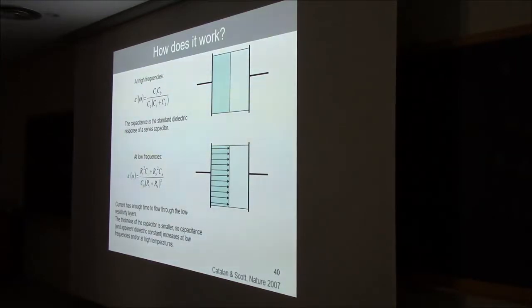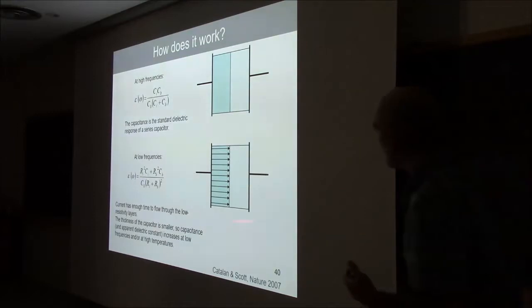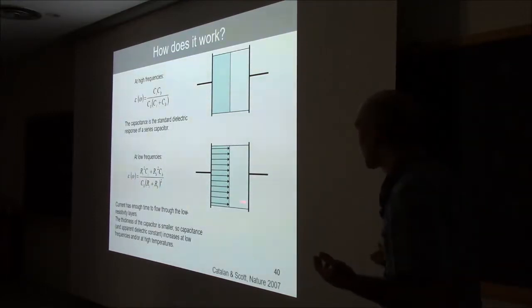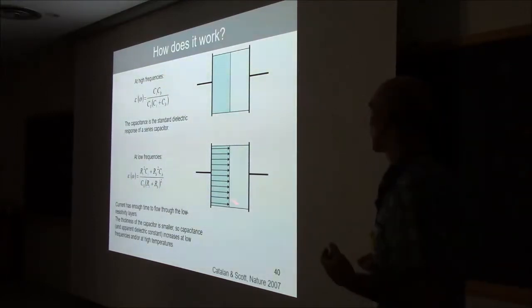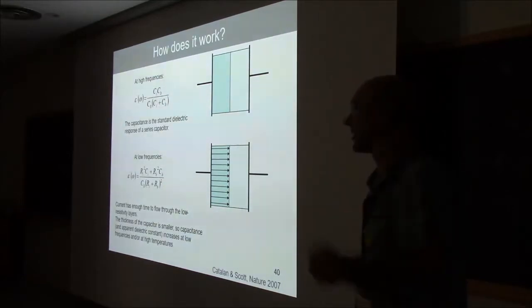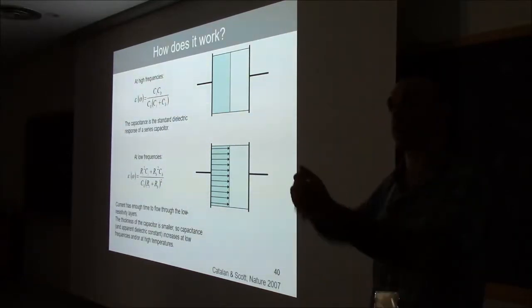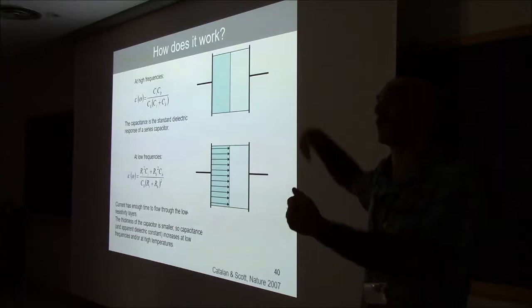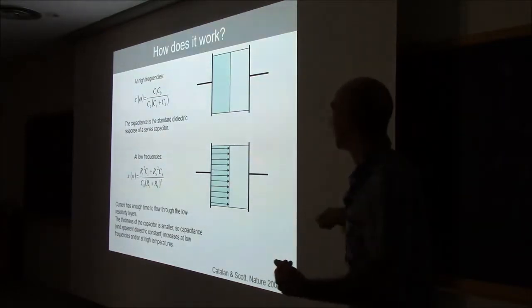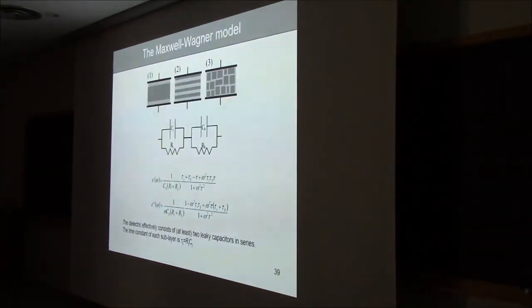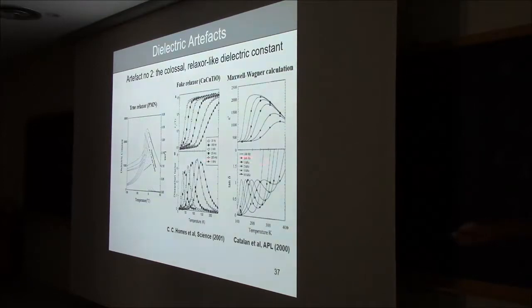So that explains the huge dielectric constant. It also explains the frequency dependence, because whether the charge flows or not depends on whether you're measuring fast or slowly. It also explains the temperature dependence, because at high temperatures things are more conducting, so it's easier to reach into this regime. So let me go back. So at high temperatures, you very easily reach into the high capacitance regime. It's a high capacitance, but it's not a high dielectric constant. Yeah?